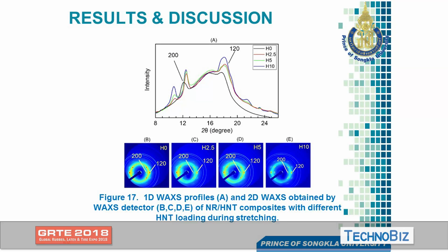Yes, we can see over here, this is the sample being stretched. Normally this peak is a hump here, and nothing happens to the diffraction peak over here. But after being stretched, as you can see, there are peaks appearing at the planes 200 and 120. These peaks keep increasing once we include more HNT inside the matrix. As we can see from the 2D image over here, the more transparent regions mean that crystallization occurs in the samples.